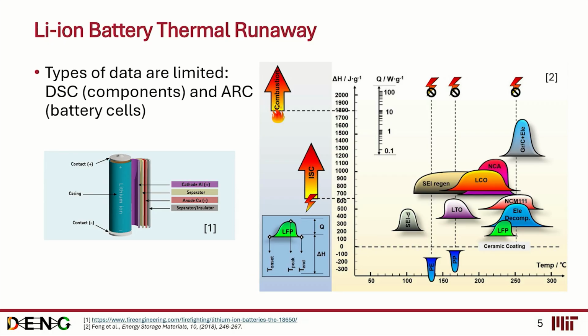As we probably already know, lithium-ion batteries have many components. They have a cathode, anode, electrolyte, and also some intermediate species, such as the interface between the electrolyte and the anode, right? That's called the SEI interface. So actually, all of the components can undergo heat release processes under different conditions. For example, showing on the right, taken from the literature, you have this interface between the electrolyte and the anode, called the SEI layer, that can become thermally unstable at as low as 80 Celsius, all right? And then you have some separators, depending on the chemistry, they might get melted down such that you can trigger the internal short circuit. Or if you coat it, then you can delay the melting down of the polymers.